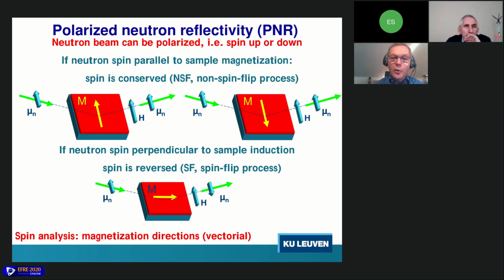And so you can have two cases. One process in which the neutron spin is conserved, that's a so-called non-spin flip process. And this provides information about the magnetization component that is parallel to the applied field. But you can also measure the amount of neutrons that reverse their spin. So this is called the spin flip process. And this will provide information about the magnetization component perpendicular to the applied field. So by doing this analysis, you can actually measure in a vectorial way the magnetization direction in your sample.